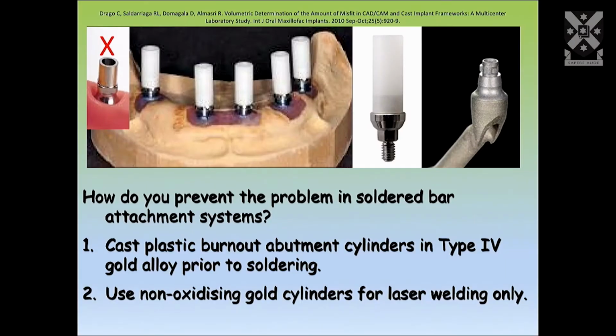So we came up with a solution to the problem. Don't use non-oxidizing gold cylinders to solder bar attachment systems. You instead order the plastic one, and you place a sprue onto the plastic, which you then burn out in a furnace and cast it through a casting process. And then you go ahead and solder your gold bars to your gold cylinders, which are now being cast. And you keep the preformed non-oxidizing gold cylinders for laser welding type situations where you don't have long heat exposure or thermal cycles.